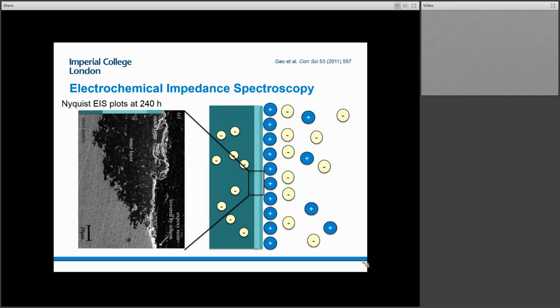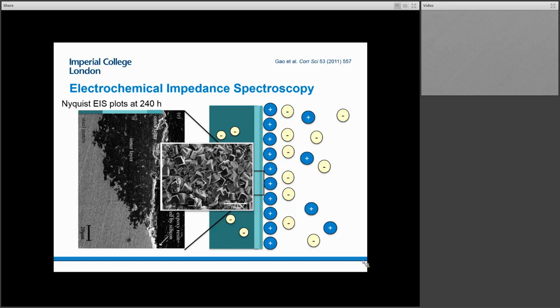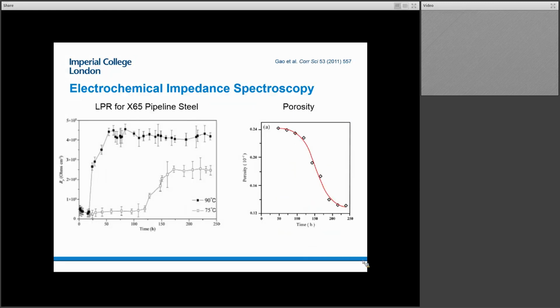And in fact, again, the outer layer now does appear to be thickening a bit. And one of the nice things, they've shown an image from the top, and one can presuppose, on the fact that they've only shown one, that it really is changing, and that is quite fascinating. But I would say they've gone one step further, which I think is really lovely.